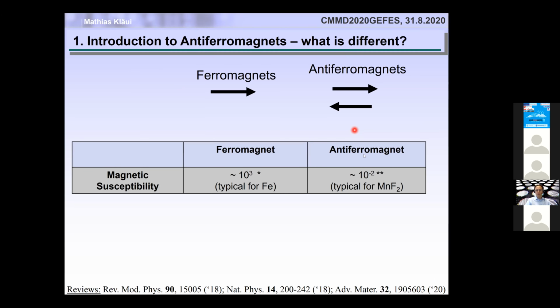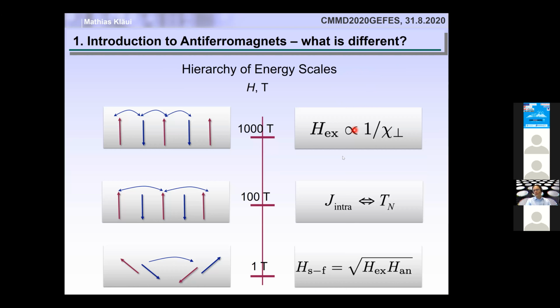And why is that? That is because if you look at the energy scales, the highest energy scale is actually the antiferromagnetic alignment of the two sublattices that you see here, which is of the order of 1,000 Tesla, and that sets roughly the transverse susceptibility. And then you can also have a strong exchange within a sublattice of, let's say, 100 Tesla. And these two numbers don't need to be so different. That sets the Néel temperature.